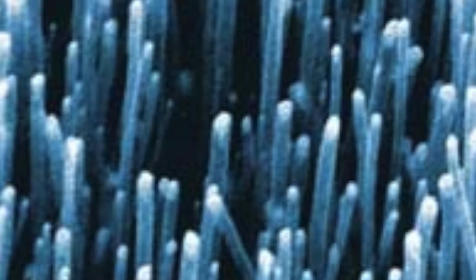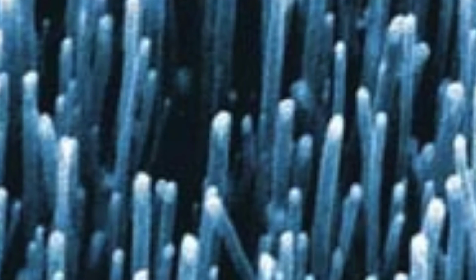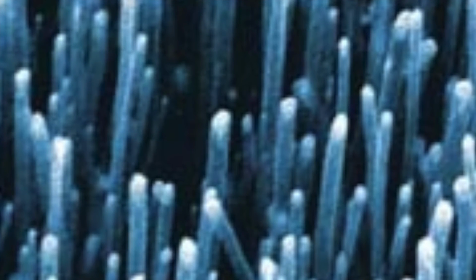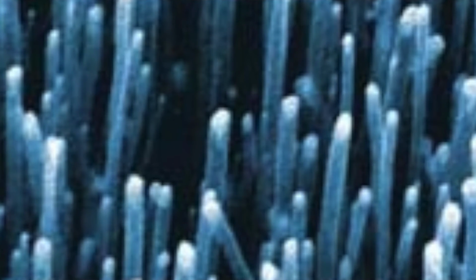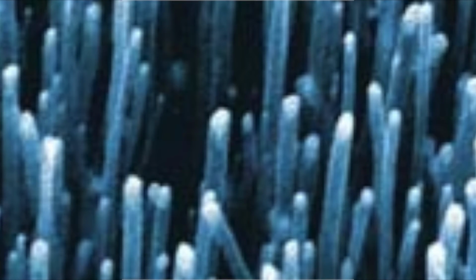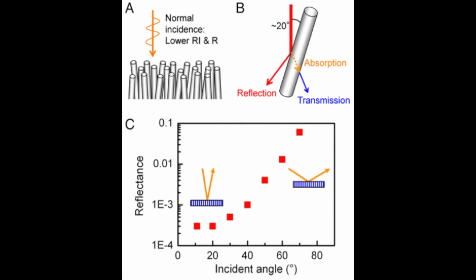Vertically aligned CNTs make up 3% of the total volume of a carbon nanotube forest, leaving the other 97% to be just air. The tubes are arranged perpendicular to the substrate, and the light enters the forest and interacts with the nanotubes. Since the tilt angle is small, little light is reflected back out. Instead, it travels around through the forest and is simultaneously absorbed by the nanotubes. This continues until the majority of the light is absorbed. The sparseness and alignment of the nanotubes in a carbon nanotube forest are the key drivers in the low level of reflectiveness of these types of materials, especially Vantablack.